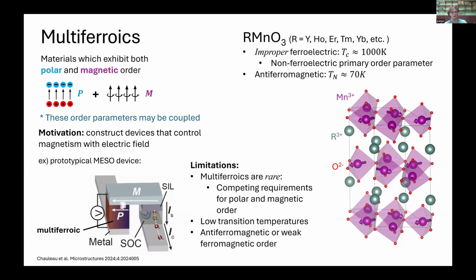And this fits into the MESO architecture that I'm sure somebody else at this conference has mentioned. But these multiferroics exist, but there are limitations on making them useful for device applications. They're in general pretty hard to find because the polar and magnetic order want different things. The ones that do exist typically have low transition temperatures, especially for the magnetic phase, and that magnetic phase is often antiferromagnetic or weak ferromagnetic. So we want to engineer materials that improve these properties.